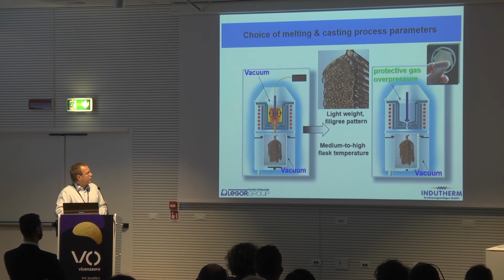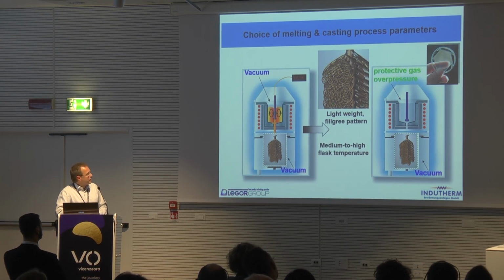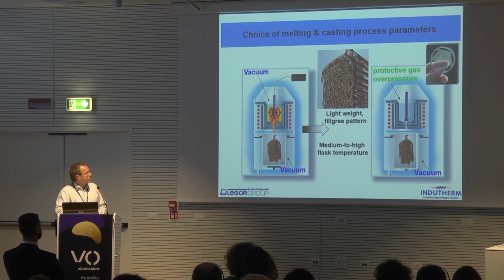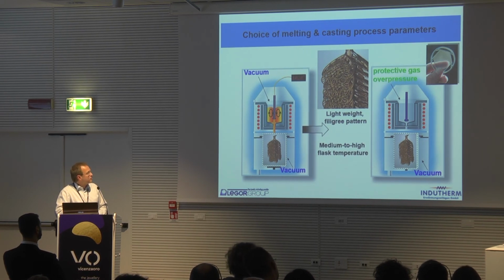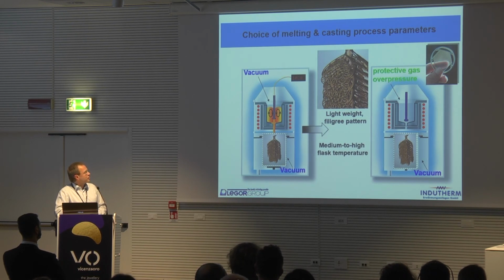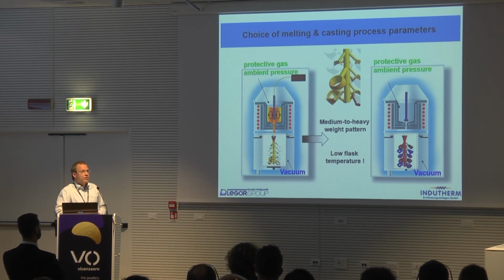We have to obtain the fill first of all, and then we have to look at the quality of the surface. And yes, we can improve the fill process by putting overpressure in the melting chamber to assist the fill, to push the metal into the cavities of the mold to obtain optimum fill. We can also assist by putting a vacuum in the upper chamber, which will effectively evacuate the mold too from the inside and the top part, from the top chamber and from the flask chamber, and that will also allow the metal to better fill the mold. So this is, let's say, a set of process parameters that we will obtain if you go to cast very filigree items. If, opposed to that, we cast more heavy parts, we have to be more careful.